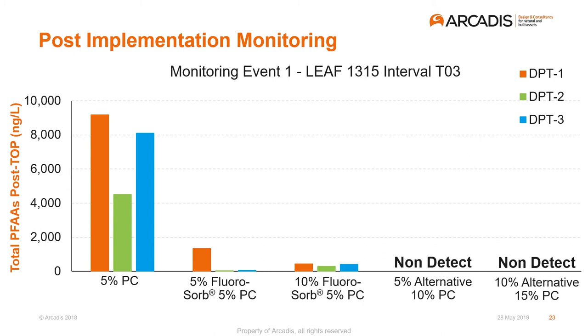And then the FLUORO-SORB showed approximately close to an order of magnitude reduction in the leachate, which is appreciable from a management strategy. And what we expect to see throughout this ongoing performance monitoring period is that we're going to oscillate back and forth between non-detect measurements and minor detections, just due to the limitations of our mixing method. So when I see three DPT concentrations that have very low variability, that to me indicates good mixing. When I see pretty variable responses when we were supposed to have homogenized the entire pit, that could be a function of either poor mixing or inefficient fixative distribution.